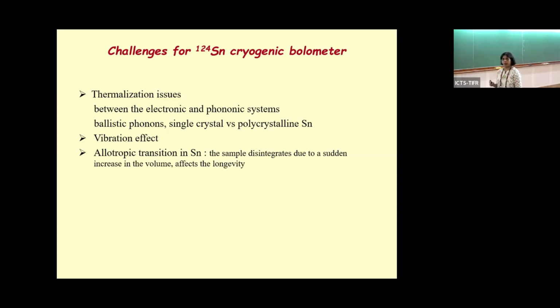Additionally, tin has a problem. Some of you may have heard of the tin pest problem. There is an allotropic transition, not at millikelvin temperature, but at low temperatures, where it can go from beta to alpha, so it just powders because of the sudden increase in volume in the transition. So you don't want to make a tin detector which has to run for 10 years, but you come back after 6 months and find it's all gone into powder. So we had to arrest that, and we had to look at various aspects.